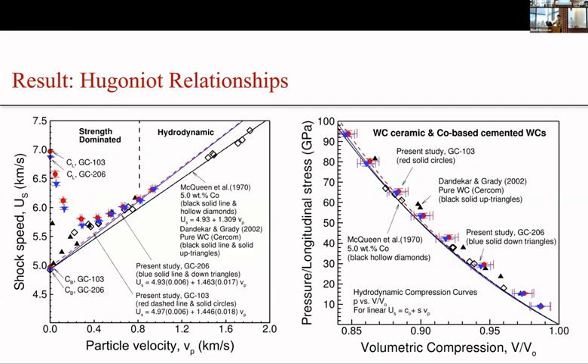The figure on the left shows the Hugoniot relationship for both grades in the shock speed versus particle velocity plane. The red and the blue symbols represent the two grades in our research. The straight lines from bottom left to top right represent a linear Us-Up relationship. Such a linear Us-Up relationship indicates the material has reached what is called a hydrodynamic equilibrium state, which means that the shear stress carried by the material is very low compared to the overall pressure, so that the material almost flows hydrodynamically. But for ceramics possessing a substantial amount of shear strength, such a state will not be achieved at low stress levels.